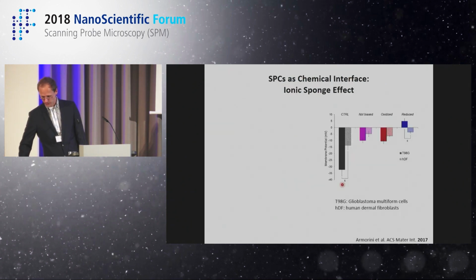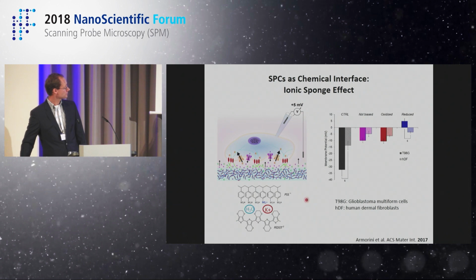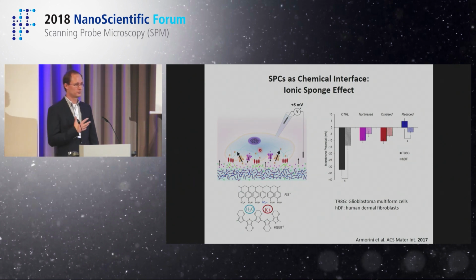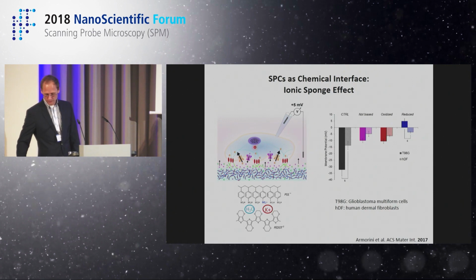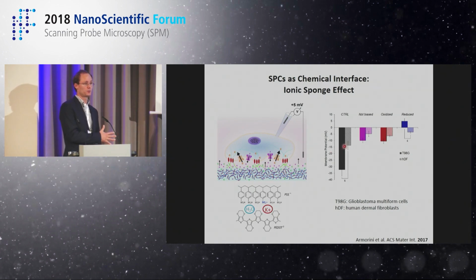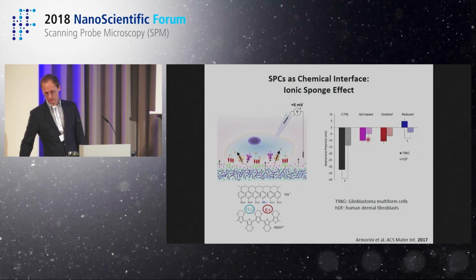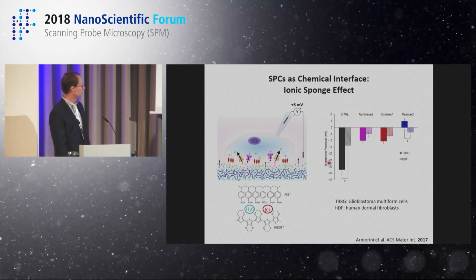Now, going back shortly just to biology, what was the system that I was investigating is a polymer composite, a cell, a lot of different interactions. The cell has to adhere to the surface, it has ionic channels, it has to do all kinds of its biochemical actions. And now what we did in collaboration with another group, we did patch clamp experiments, and we did these on differently oxidized or reduced polymer composites. And what we observed is that, in fact, the electronic state of our polymer impacts strongly on the bioelectronics of the cell, in particular on the membrane potential.